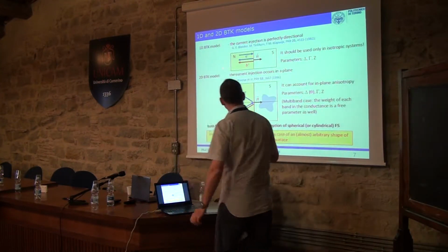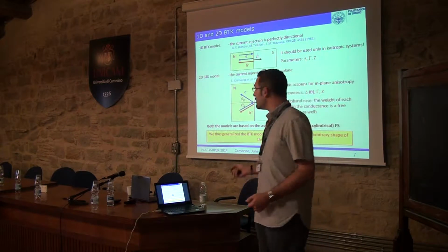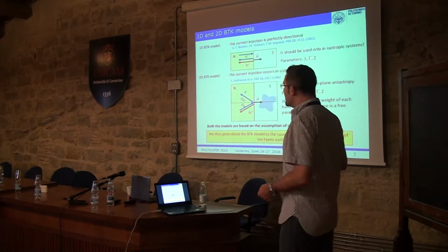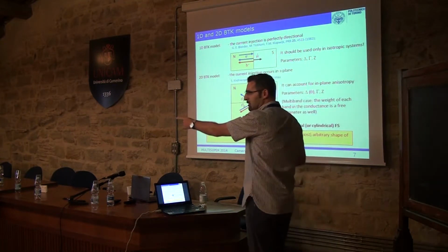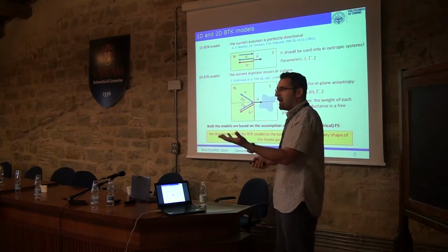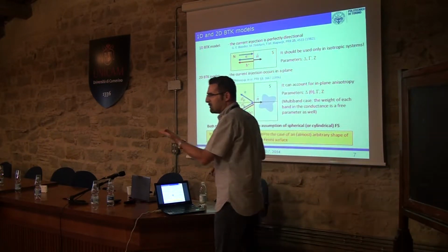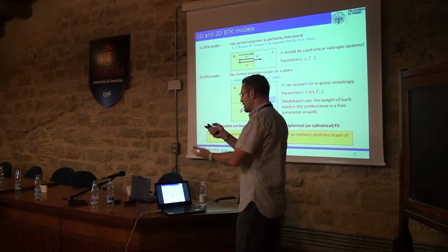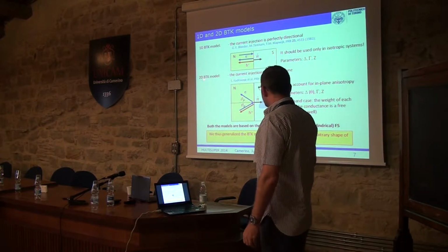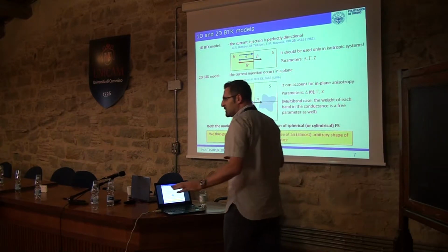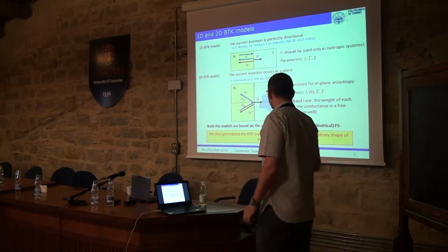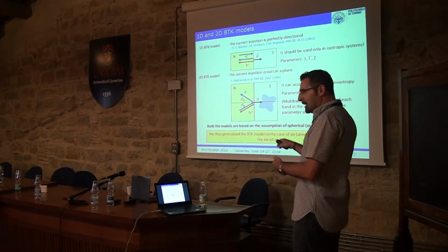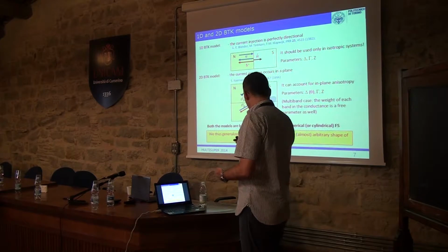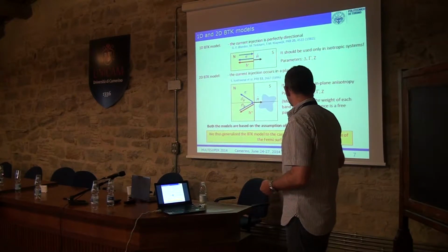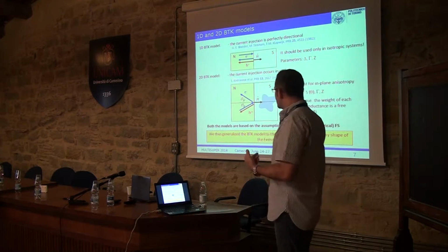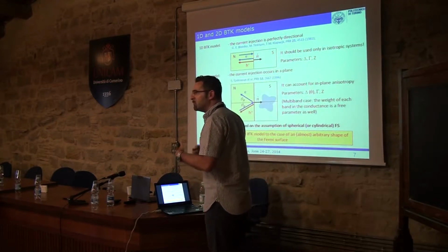The first model was the 1D BTK model. It dates back to 1982. It's for only one direction of injection, so it can be used only when you have an isotropic order parameter, because you lose completely the dependence on the direction. The 2D BTK model, which is the one mostly used in most of the papers, can account for an in-plane anisotropy like in cuprates, but it has also 3 parameters. Normally, this is also used for MgB2 and so on in a multi-band case.